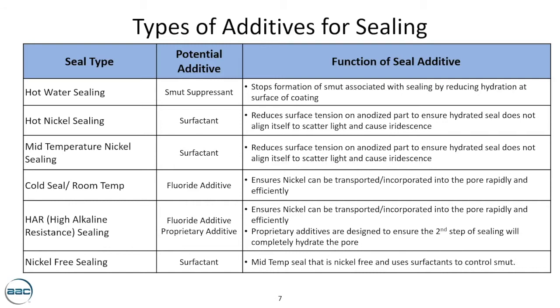And then the final sealing method, nickel-free sealing. Again, this uses a surfactant to control smut, much like the mid-temp surfactant. And again, you'll fight the same battles you're fighting with any surfactant-based sealing: over time it breaks down, and as it breaks down, you run the risk of losing seal quality.